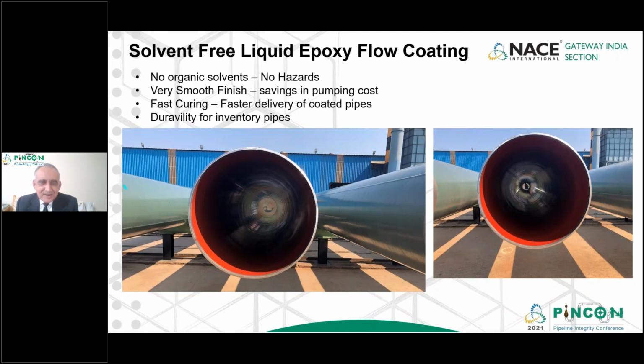So the advantage for the applicator is that once the pipe is coated, within 5 to 6 hours the product is cured, can be inspected, certified, and dispatched. So they don't occupy a lot of space in their yard, and they can increase the speed of production, and their output will be very high, like high productivity. They can dispatch the pipe within 6 hours, clear the space, and coat new pipes. So applicators are very happy with this, and it's not only the applicator, it's also high performance because the RZ value with this kind of coating is less than 1 micron, which is very smooth. For the normal solvented product, we get like 8 to 10 microns. With the solvent-free product, we are getting 0.5 microns RZ value. So it's really smooth and a lot of benefit in terms of operating the pipeline.